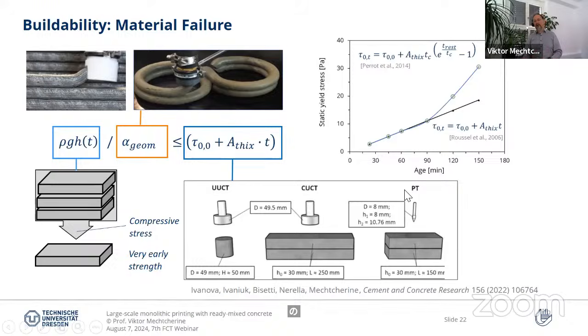So we usually recommend here to use penetration tests like this, or this kind of compressive test, either on a separate material or, of course more practical, to have some pressure on the deposited layers. Good. Again, I cannot go into much detail, but if you are interested in more information on testing as such, you can read this paper, which is published in Cement and Concrete Research. Well, and then, as said, one